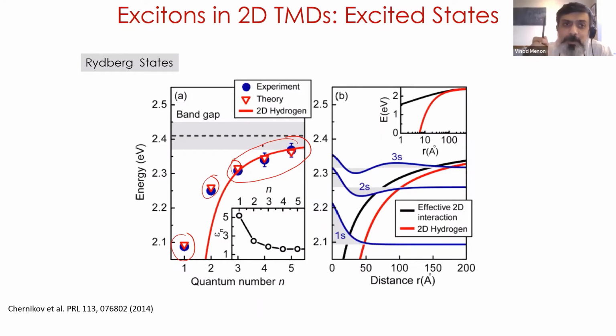But the most important take-home message from this slide is the fact that the wave functions are now much more delocalized, or in other words, they become much bigger. So the advantage here is when these wave functions become bigger, they can interact with each other much more. It's much more likely that they will interact with each other. So, for example, this one is localized to under about 25 angstroms, whereas if you go to this one, you can get up to 100 angstroms. So you get a much larger Bohr radius, which means they interact much more easily with each other.